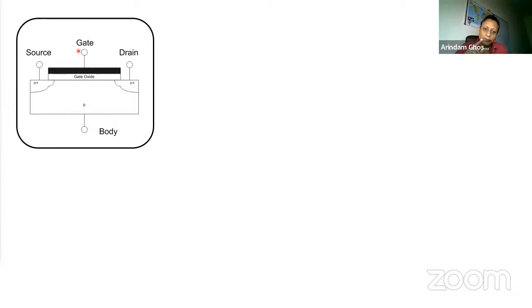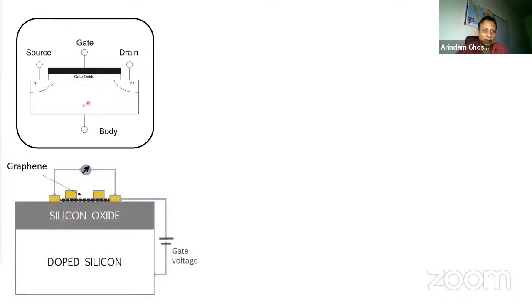Now, what the original discoverers of graphene did is they used graphene in exactly the same manner. They created an oxide, which is silicon oxide, and then they put a doped silicon, which is like a metallic gate, and then they put electrical leads to act as source and drain. And then you apply gate voltage, which changes the electron density in this channel, and that changes the current or the resistance of this channel of graphene. So this was the original device structure that was made with graphene way back in 2004.